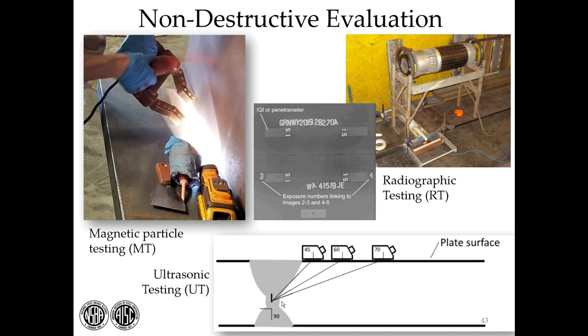And we'll say, oh, there's some problem in here. So by moving the transducer around, the technician can assess how much of a defect there is in the weld. If you have thicker material, then a 60-degree probe is used, and then for very thick material, a 45-degree probe is used. I've drawn them all here just to indicate them, but you would choose one or the other, primarily based on the thickness of the steel.